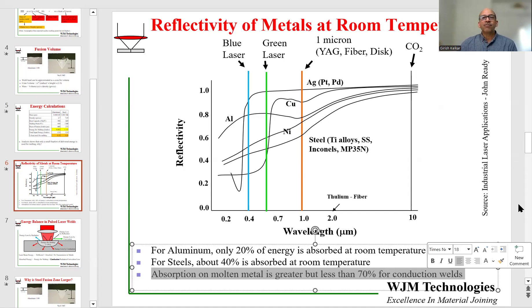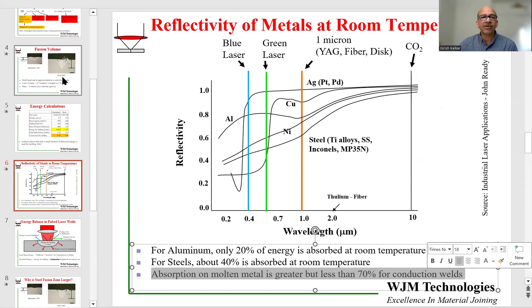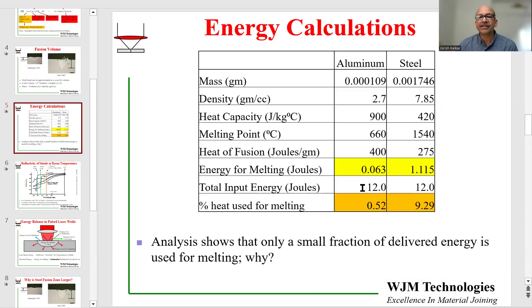As the energy is absorbed, the material starts to melt, and as materials melt the absorptivity increases — so a greater fraction of incident energy is absorbed on molten metal compared to solid metal. But that still doesn't go close to 100%. Even in deep keyhole mode welds, absorption is somewhere in the order of 70 to 80%. In this case we are almost in conduction mode, maybe slightly bordering keyhole in steel. So even in the molten condition, absorption is of the order of 50% to 60% — fairly low. A lot of the energy you are supplying is actually being reflected, with close to 50% already lost.